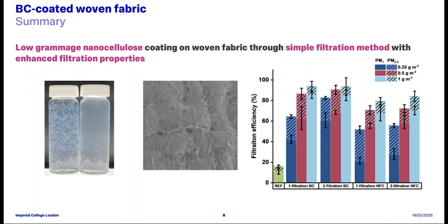For instance, we can observe agglomeration of bacterial cellulose in the suspension state, especially when we compare it with the cellulose suspension from other sources. And these agglomerations then lead to pinholes or defects in the resulting coating layer and subsequently cap the particulate filtration efficiency of the resulting coating layer at the maximum of 85% for PM1 particulates. We're thus very curious if there's a way to optimize this system and improve the dispersion of bacterial cellulose in suspension.